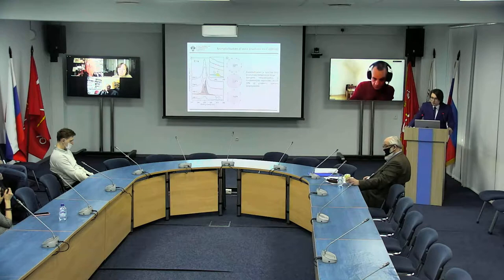And based on these results, we compiled our first conclusions. The graphene synthesized on cobalt surface is characterized by lattice strain reaching 0.6% for polycrystalline and 1.8% for single crystalline graphene. And the detected G band in the Raman spectra of single crystalline graphene on cobalt substrate is due to non-resonance scattering in contrast to the resonant one. So let's shift to the next part of the results.